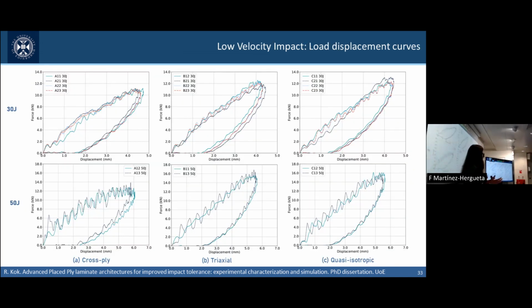And these are the first results, the force displacement curves. The first good thing is that apparently there is not a massive influence on the impacted point. All the curves are quite repetitive for all laminates and for all impact energies. The triaxial and the quasi-isotropic laminates perform very similar in terms of stiffness and maximum loads. But the cross-ply laminate presents a poorer impact response. In particular, it reaches a maximum load capacity of around 12.5 kilonewton. And this plateau indicates that with 50 joules, we have activated a catastrophic failure mode definitely.